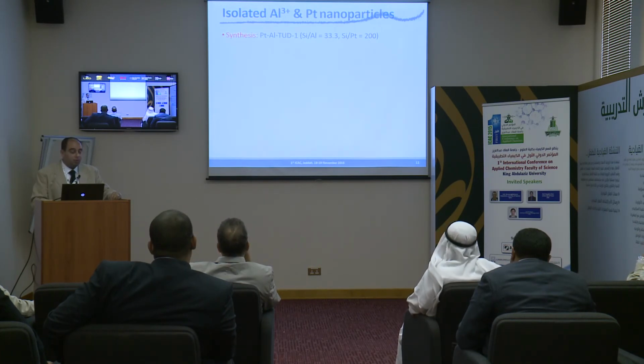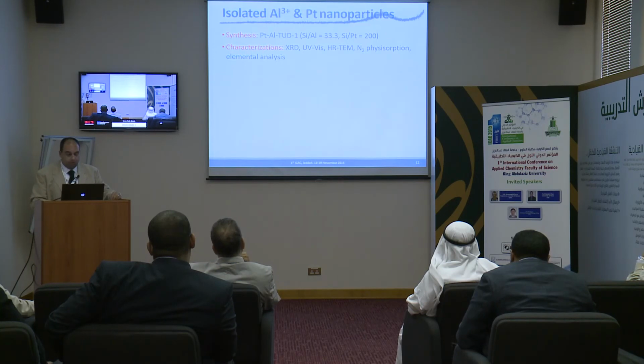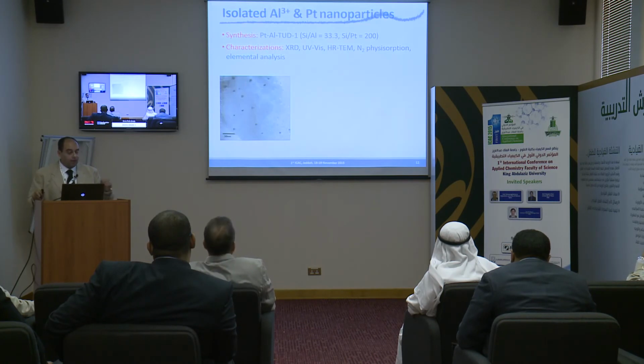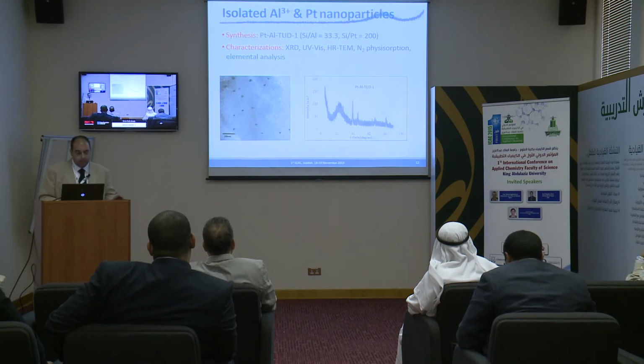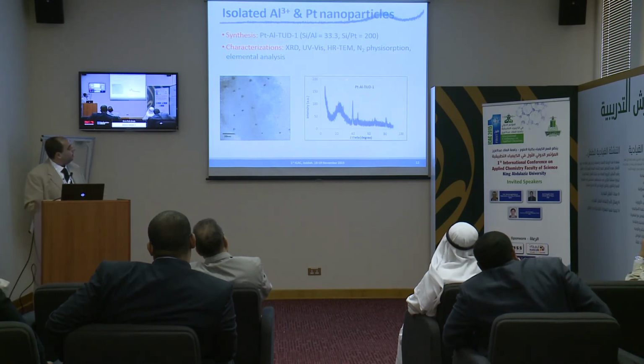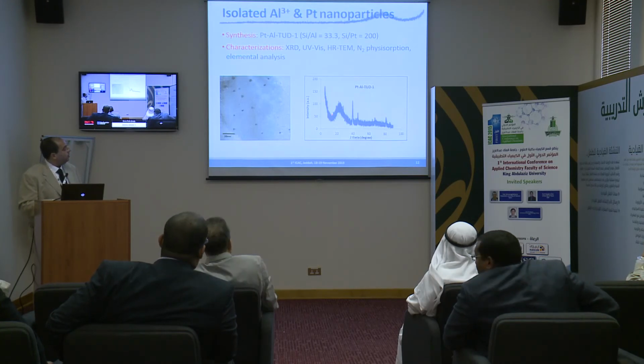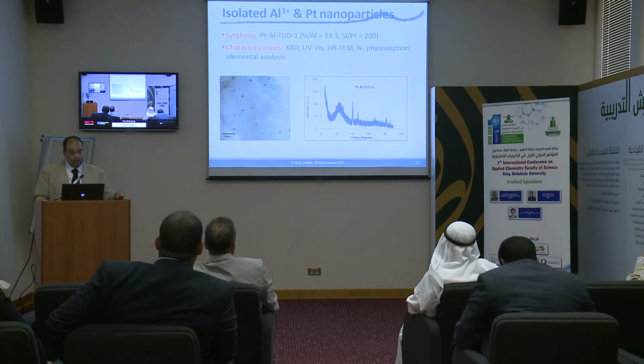Well, this is the material that we prepared. We prepared aluminum platinum TUD1 with different ratios. We characterized the material with the available characterization techniques at King Khalid University. This is a high resolution TEM of this material, and you can clearly see the highly distributed particles of platinum in the silica matrix, and the XRD confirms the presence of platinum as well. You don't see here any peaks for aluminum, as an indication of the total incorporation of aluminum in the silica matrix to generate the acidity.